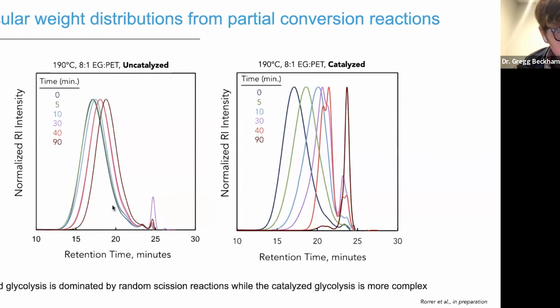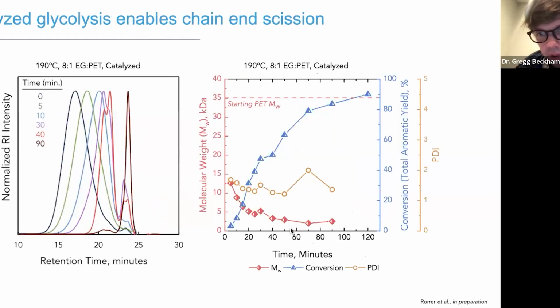You can see, as you would expect, a reduction in molecular weight in the uncatalyzed case, but it's not very dramatic. Whereas when you have the catalyst around, triethylamine, you get essentially only small molecules present and very little residual oligomers. What this suggests to us is that uncatalyzed glycolysis is dominated by random chain scission, and the catalyzed glycolysis chemistry is much more complex. So we're quite interested in building a kinetic model and a mechanistic model of this chemistry as well.